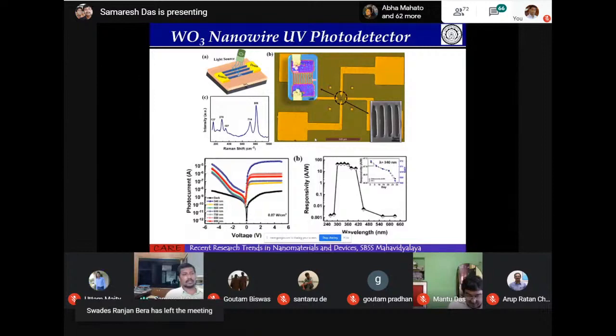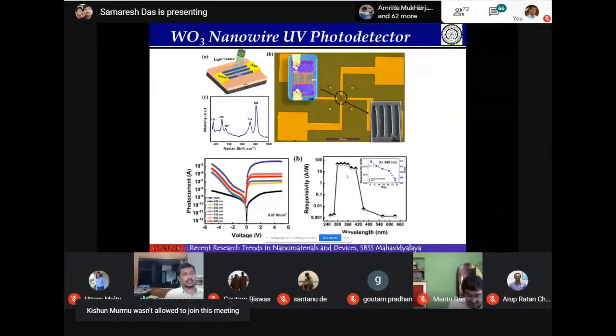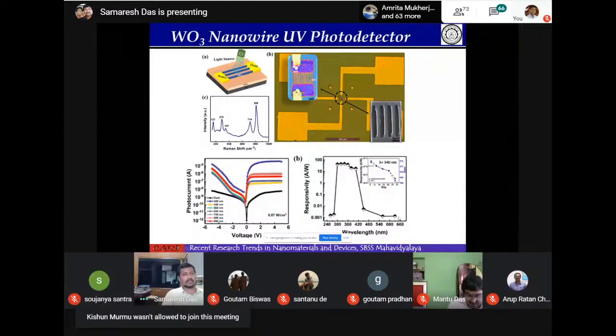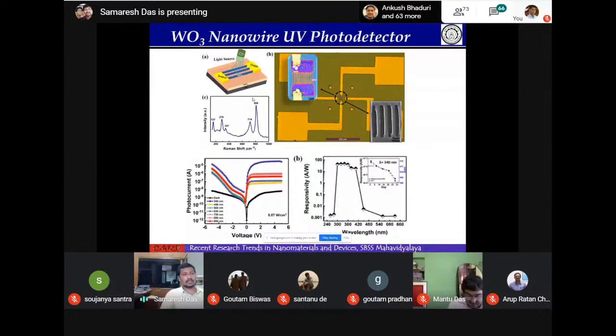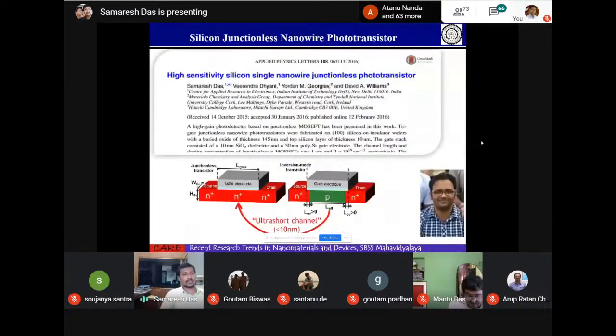Because of the nanowires, the transit time is fast, and you can see the detected responsivity. It is mainly for the UV range, and then there is a sharp fall in the responsivity in the visible range. So this is UV band detection, and we have shown that because of this nanowire, the transit time is very fast. You can detect sub-microsecond photodetection. And also we are working on the visible and near infrared for the silicon technology.